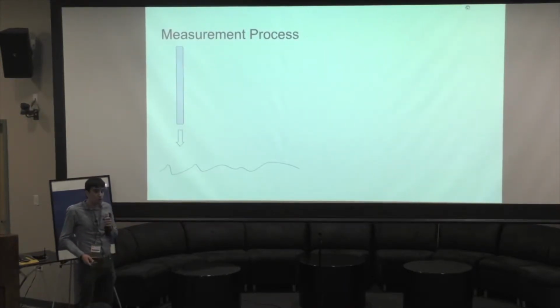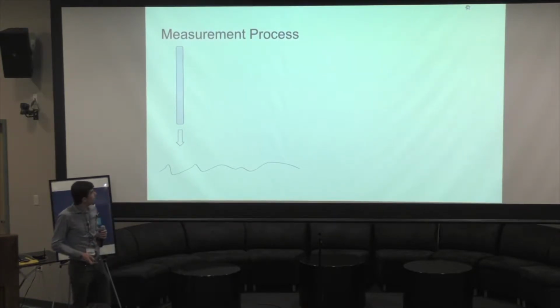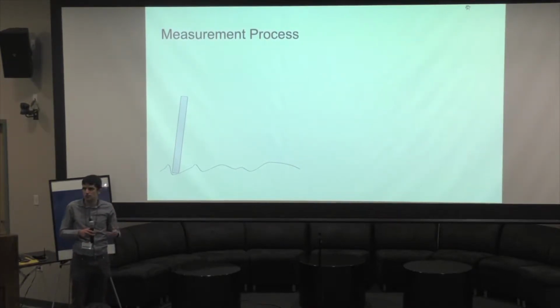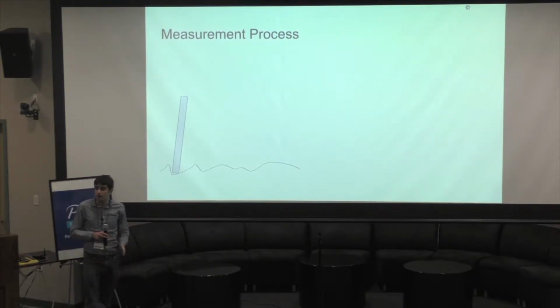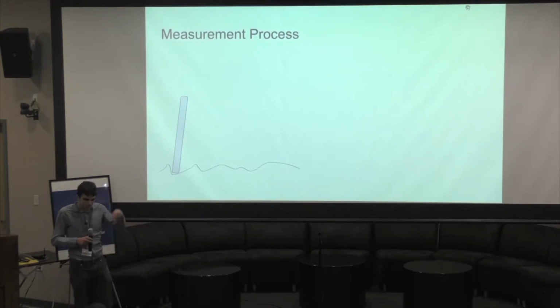So the protocol that we're using for these measurements has two steps. First, we approach the cantilever to the surface, and we detect the position of the surface by looking at a DC change in the interferometer power caused by the cantilever deflecting, basically very crude pinpoint AFM.